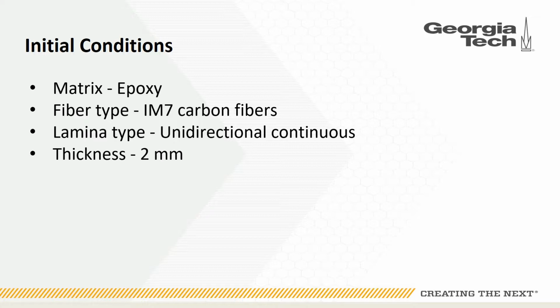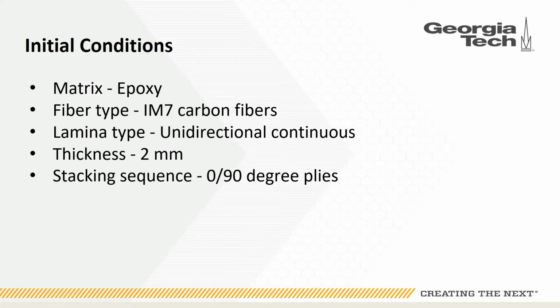For thickness, we wanted to consider that the thinner the lamina, the more in plane the stresses were, and this was one of our assumptions. Therefore, we tried to go as thin as we could without requiring too many plies. So we chose a standard thickness of 2 millimeters based off of prepregs available. For the stacking sequence, due to there not being any shear forces applied, we decided to only use plies in the 0 and 90 degree directions. And for our volume fraction, we started with 0.6 because this was what was commonly seen in the textbook and in the examples that we did in class.